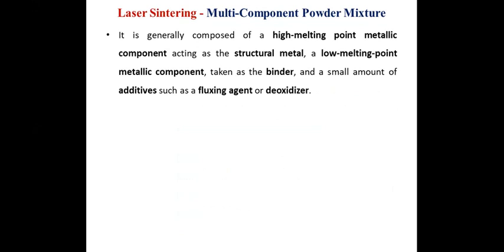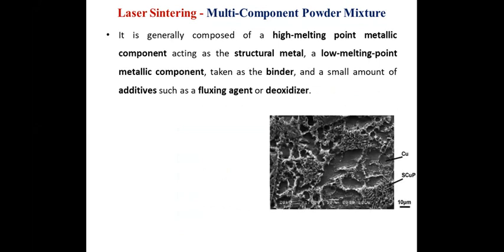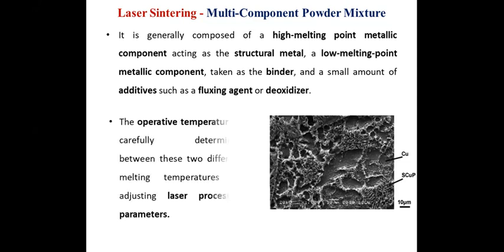A multi-component powder mixture is generally composed of a high melting point metallic component, a low melting point metallic component taken as the binder, and a small amount of additives such as fluxing agent and deoxidizer. The composition influences the microstructural properties. The low melting point metallic components will be melted and bond the high melting point metallic components. The operative temperature is carefully determined between these two different melting temperatures by adjusting laser processing parameters.